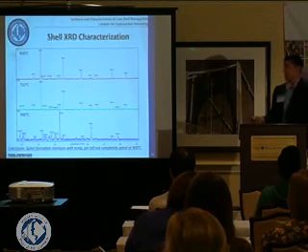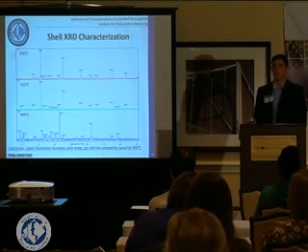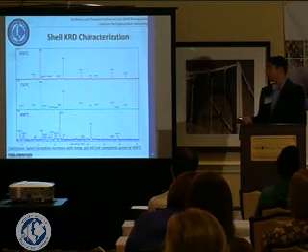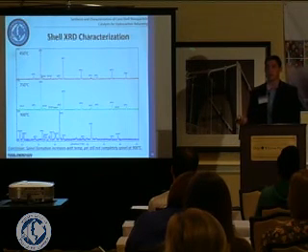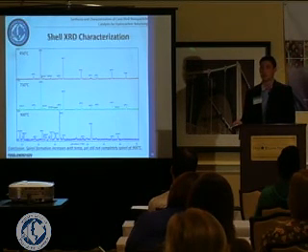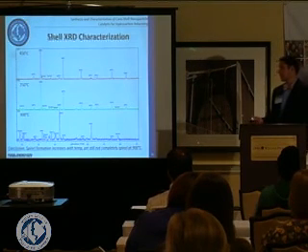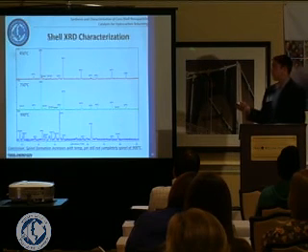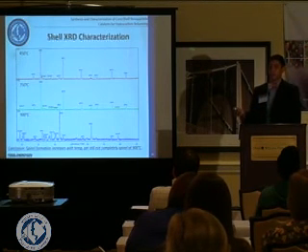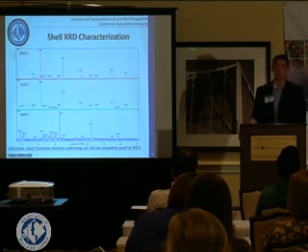I then went through and made the shell by itself because the spinel versus oxide form of the shell isn't really well understood. So I calcined at 3 different temperatures. Calcined is basically just heating really hot to turn the hydroxides into oxides and to also have a solid state reaction between the oxides. I found that going from 450 to 900 degrees C, more of the peaks were spinel and less were just metal oxides, which is good. But at 900 degrees C, where my reaction occurs, you still don't have completely spinel, which is important to note.